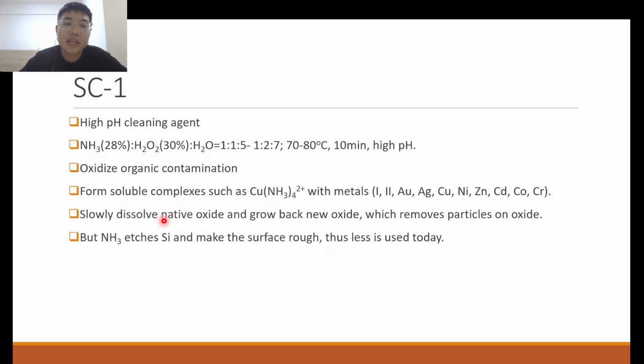And so the good thing is that this cleaning agent is also able to slowly dissolve the native oxide layer on silicon, and eventually a new oxide layer will grow back. That's good because it removes the particles on the oxide. You can think of it, the particles are resting on your silicon surface, with a thin layer of native oxide. So when this cleaning agent removes the layer of native oxide, it removes the particles together with it. That is because ammonia is able to lightly etch away silicon. But the problem is that this will make the surface a bit rough, and so sometimes you will tune the ratio of ammonia to be lesser.